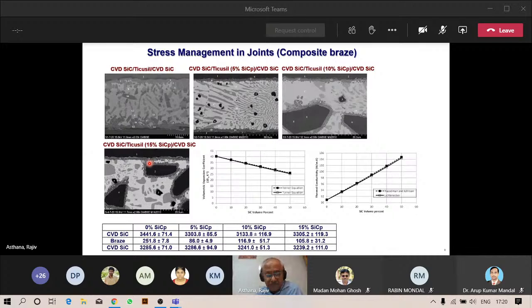Conductivity of the braze region will go up when you disperse a judiciously selected reinforcement. Of course, in the case of silicon carbide particles, if you're using an active braze like TiCuSil, which is titanium, some of the titanium will be lost in the reaction with the substrate, and some will be used up in reaction with the particles. So you may have to control the amount of titanium in the braze to get the right thickness of the reaction layer.